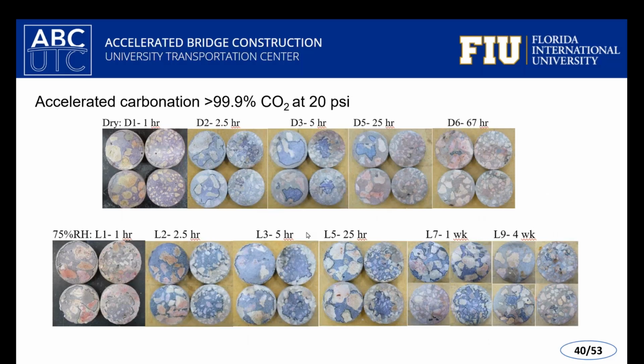Here's an example of similar concrete, just to identify the rates at which carbonation can occur. So these are all samples of concrete kept in either a desiccated environment or a controlled environment at 75% relative humidity. And you can see when placed into these carbonation environmental chambers, by the color indicators, that in a very short amount of time carbon dioxide gas can penetrate very, very quickly. And that's indicated by the loss of the purple colors over time.